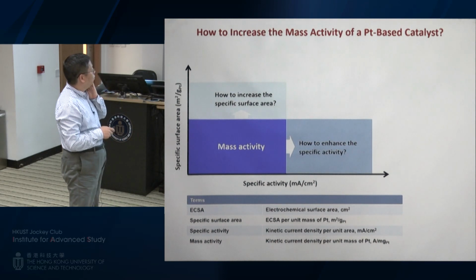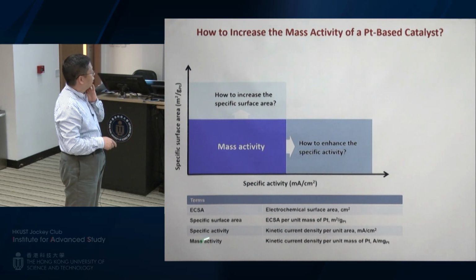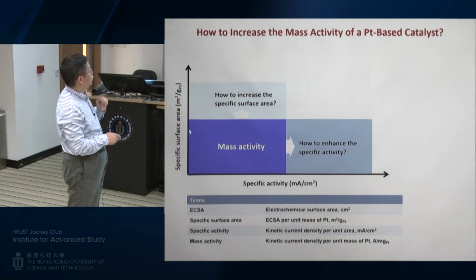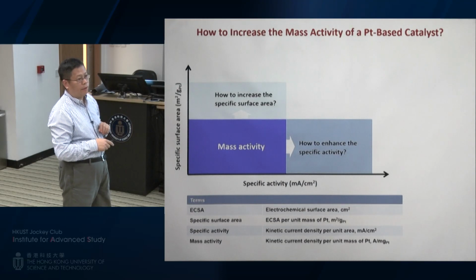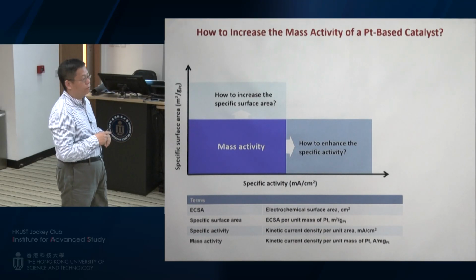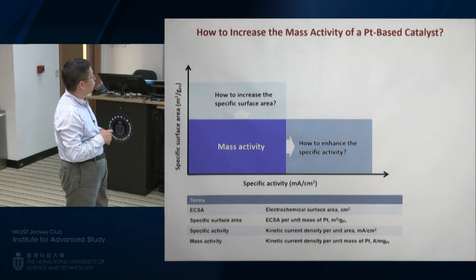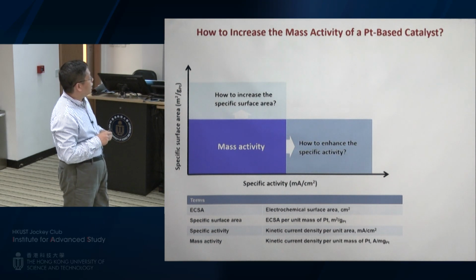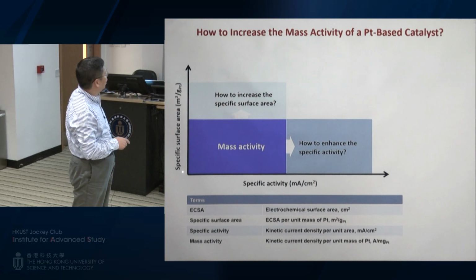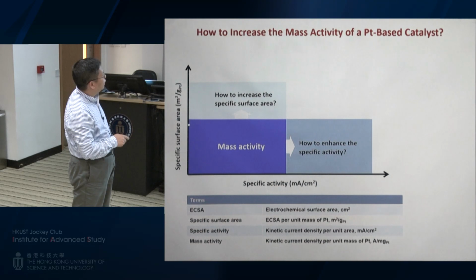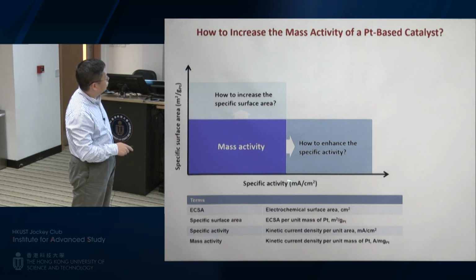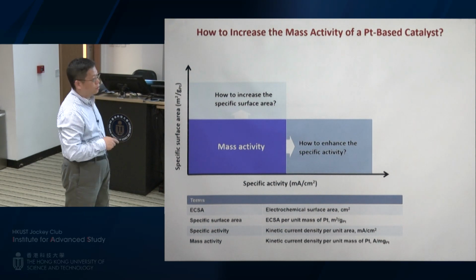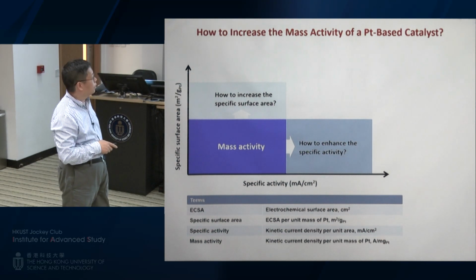So now let's see how we can find a better use for this. What's really important is the mass activity. That means how much current you can draw per unit mass of the platinum. That will tell you how much catalyst you need to deposit on the cathode. The mass activity is a product of two parameters: one is the specific activity, another is the specific surface area. If you want maximum mass activity, you would like to maximize both specific activity and specific surface area.